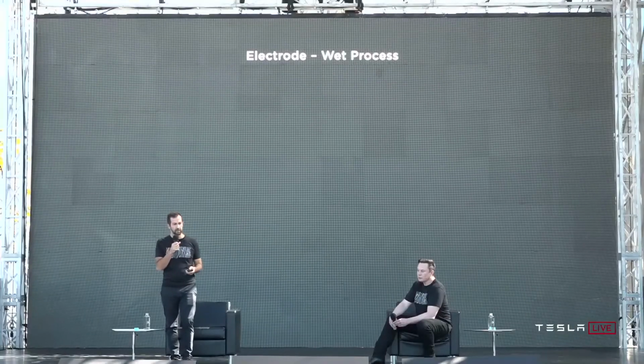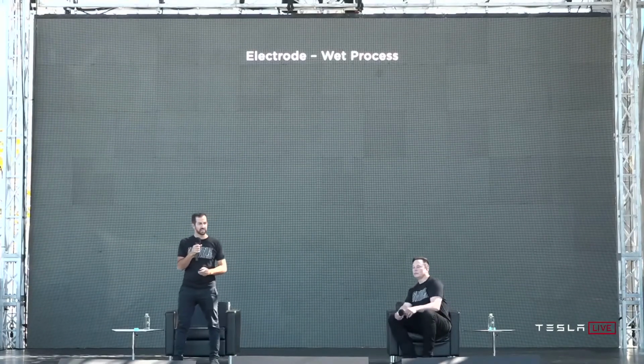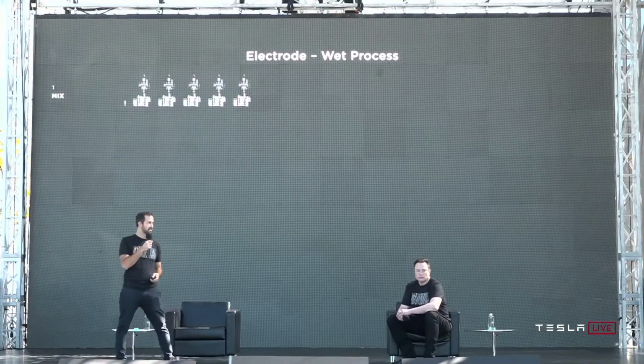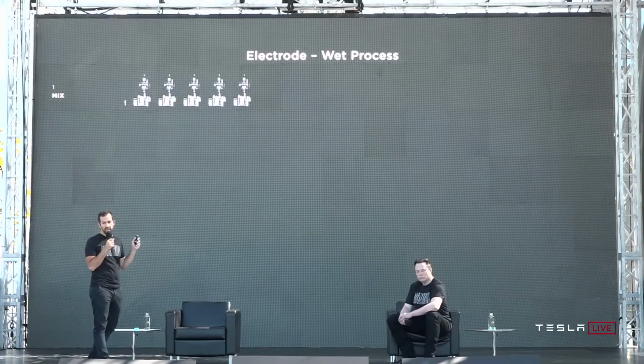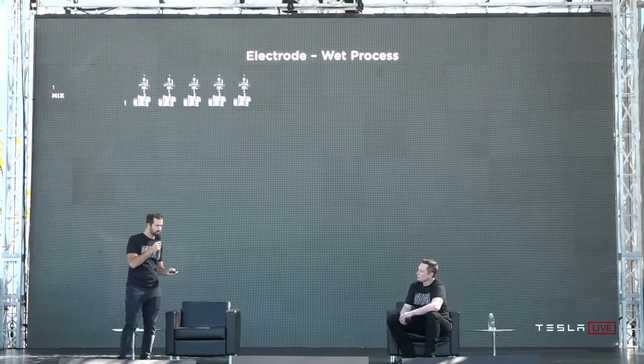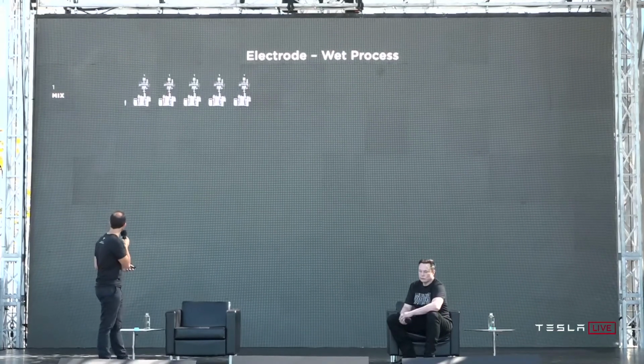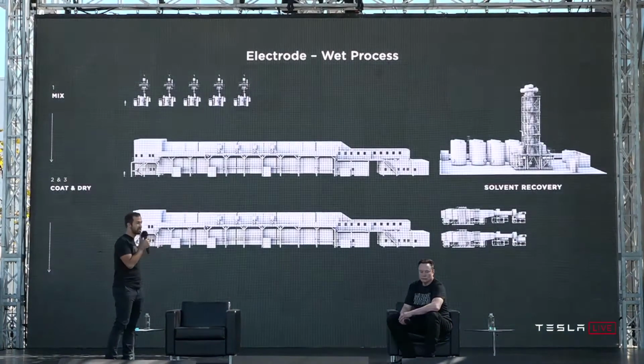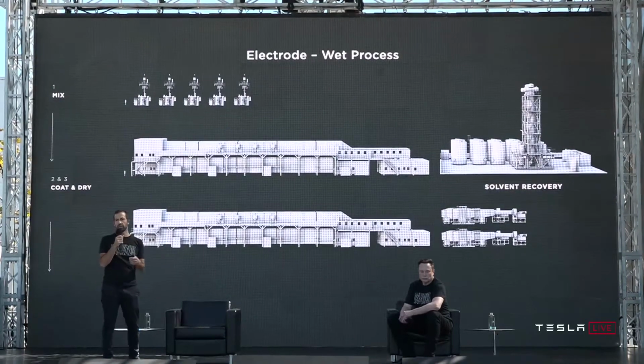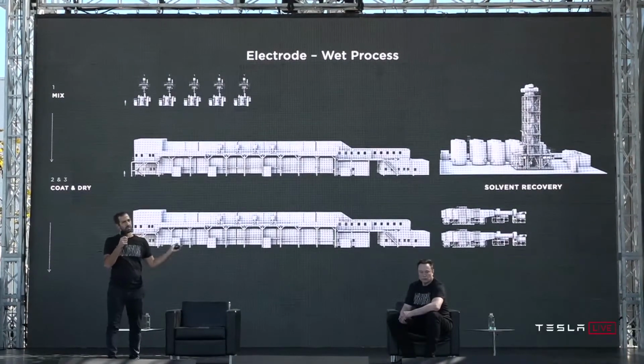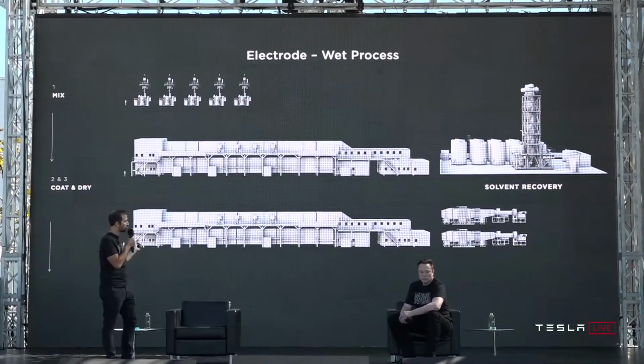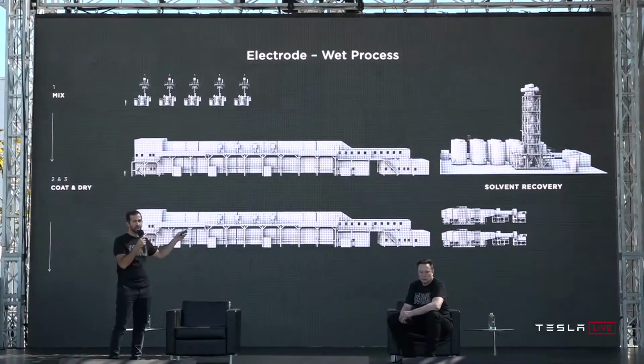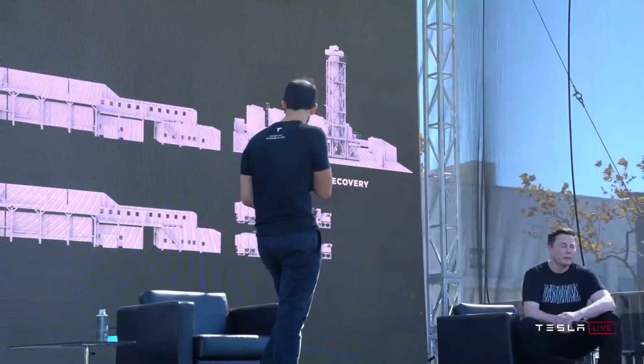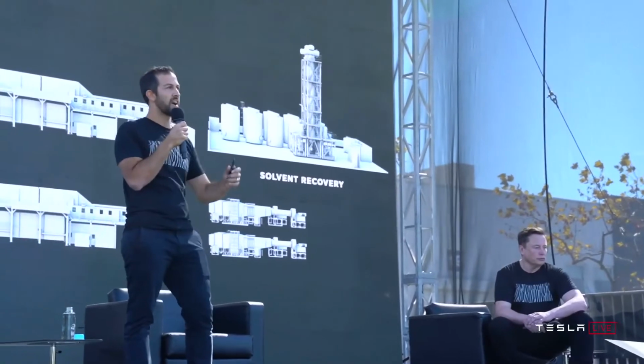One of the most important processes is where it all begins, the wet process of the electrode coating. Just to give you a sense of scale, I'm going to walk through what's in that wet process. You've got mixing, where the powders are mixed with either water or solvents for the cathode. That mix then goes into a large coat and dry oven, where the slurry is coated onto the foil, huge ovens, tens of meters long. It's dried, and that solvent then has to be recovered. You can see the solvent recovery system. And then finally, the coated foil is compressed to the final density.